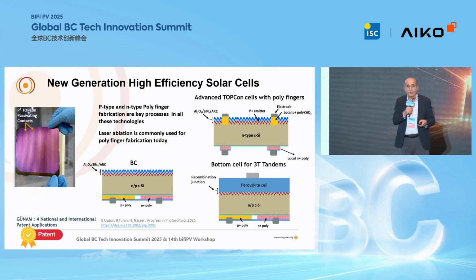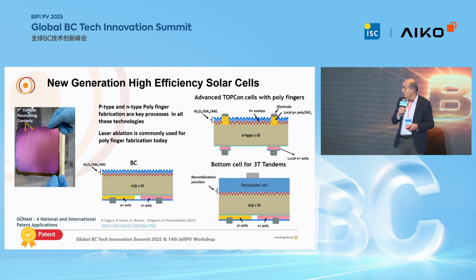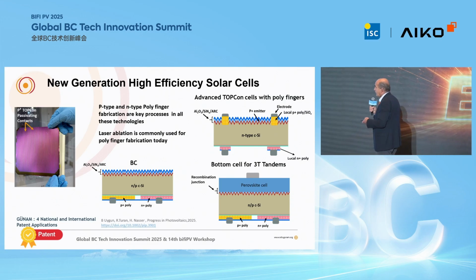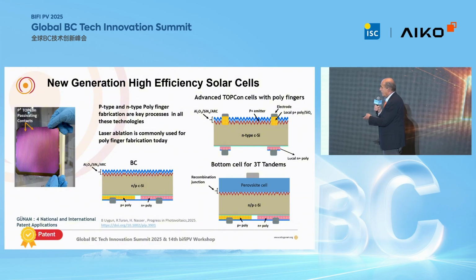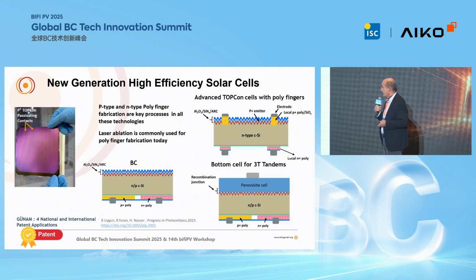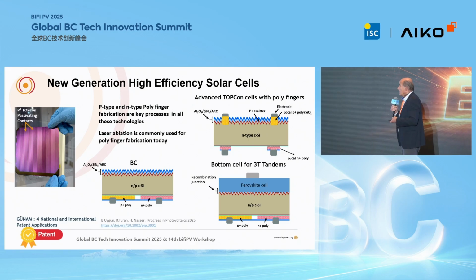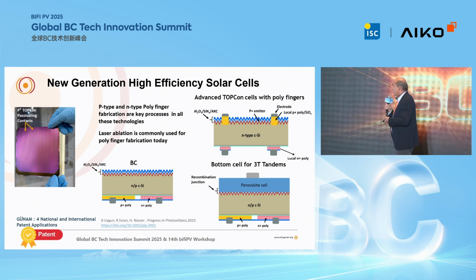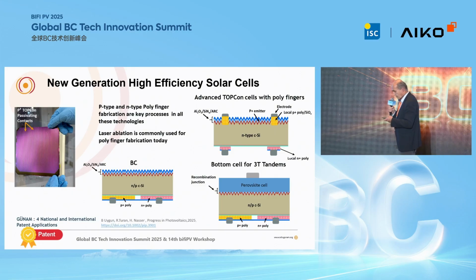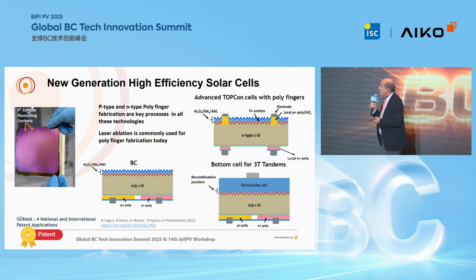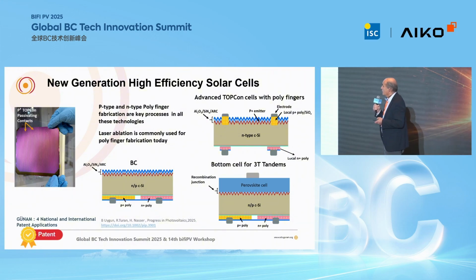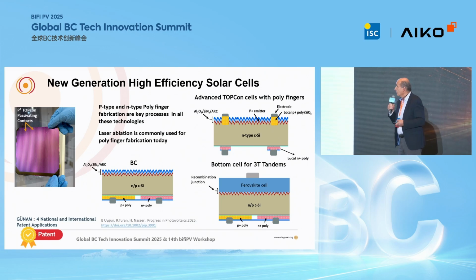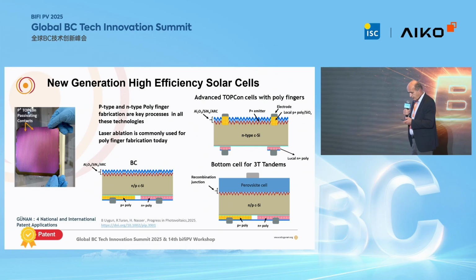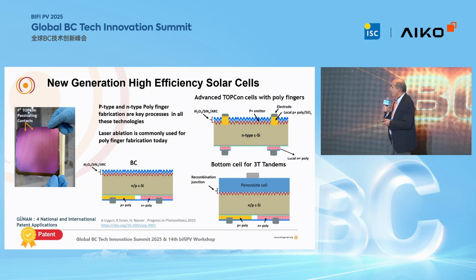Some companies have already implemented this, especially on the back side, so it is commercially available. For the BC case, we have, of course, poly fingers on the back side. So patterning poly is a critical parameter, a critical process, and this will also remain critical in the next technologies like 3T tandem. So we will still have the patterning on the back side. So this has been successfully done by laser ablation so far. We have seen a lot of approaches using laser ablation by companies, also by institutes,